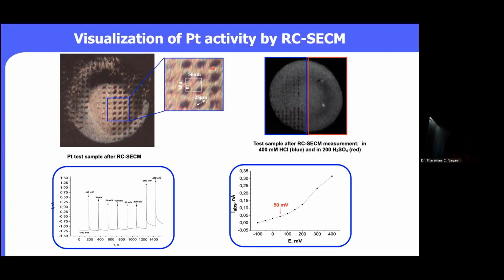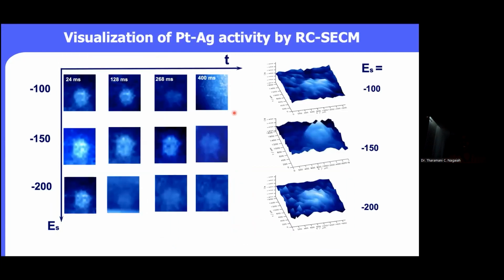Therefore, whatever the black spots are, they are due to the etching of the surface due to the dissolution of the platinum chloride here. So we want to stabilize this one. We have chosen silver as a catalyst here. What we did is that we have electrodeposited platinum silver. The aim is that the silver potential is quite low, around 0.8 volt compared to the platinum, which is 1.2.